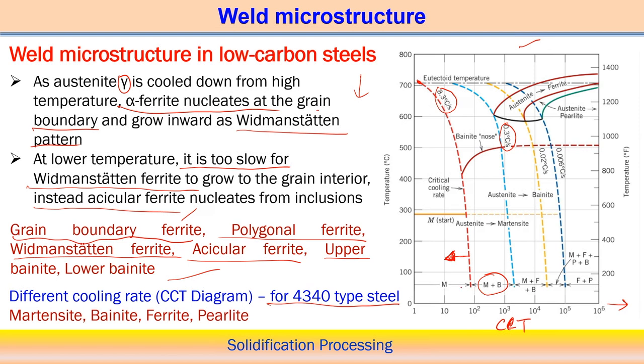And of course, if you see, this is the time frame, also the x axis. So when you are getting the martensitic structure, the required time is very low. Very quickly, if you follow the high cooling rate, at very low time we are getting the structure. So basically diffusion time is reduced, then we get towards the martensitic structure. But if you allow more diffusional time, the diffusion occurs, then we will get a mixture of martensitic plus bainite.